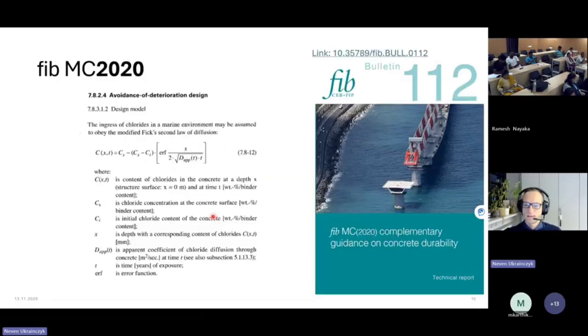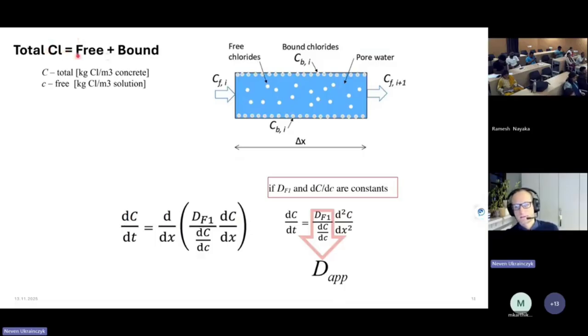So here we consider the total chlorides, meaning the free and the bound chloride. So the total is free plus bound. If this is a pore, we have the chlorides that are bound to the solid, and we have the free in the bulk pore solution. So this would be the bound, and those are the free chlorides. If you do the mass balance, the total is in kilogram chlorides per cubic meter of concrete, and the free chlorides are in kilogram chloride per cubic meter of pore solution.